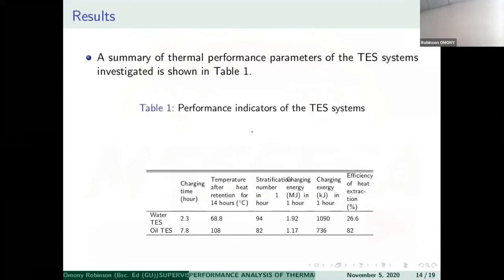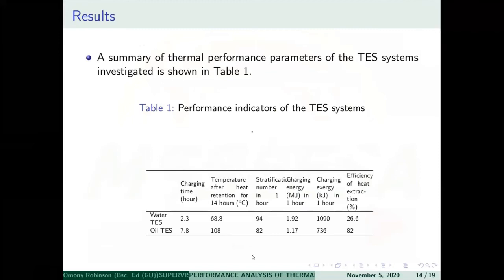Now this is a summary of thermal performance parameters of the TES systems investigated. So the charging time for water was 2.3. Meanwhile, that of the oil TES was 7.8, because it was supposed to reach a fairly high temperature that would allow for cooking. Then temperature after retention for 14 hours, as I said earlier on, was 68.8 averagely, then 108 for oil.